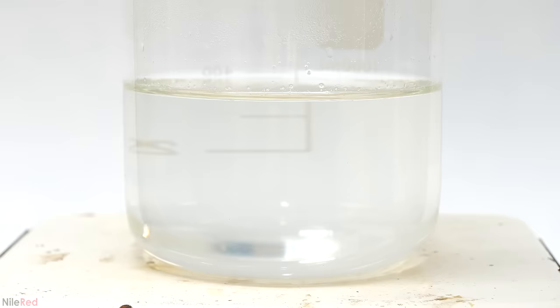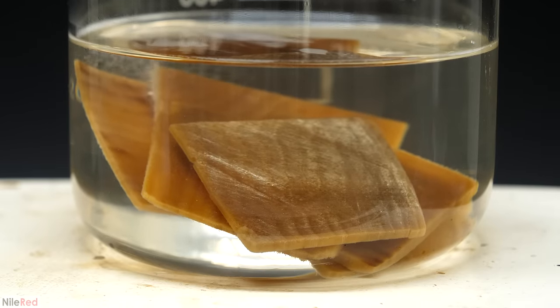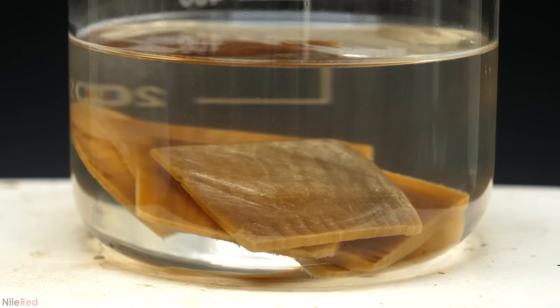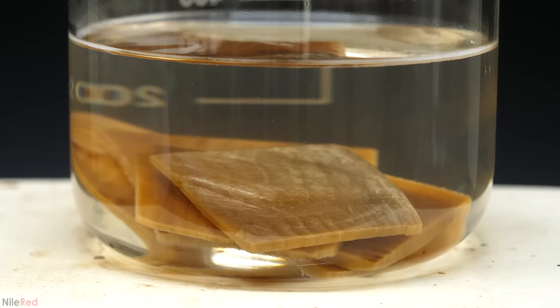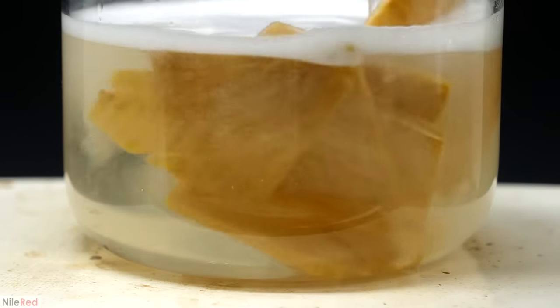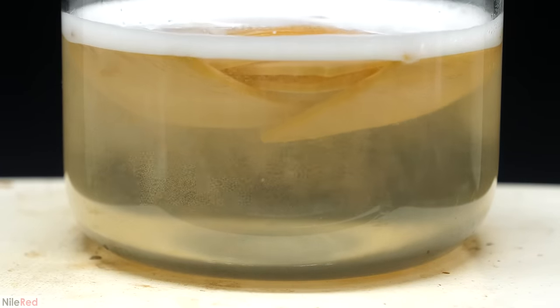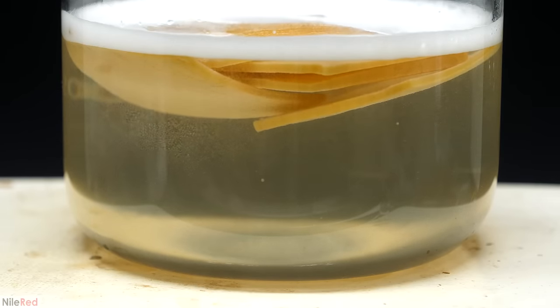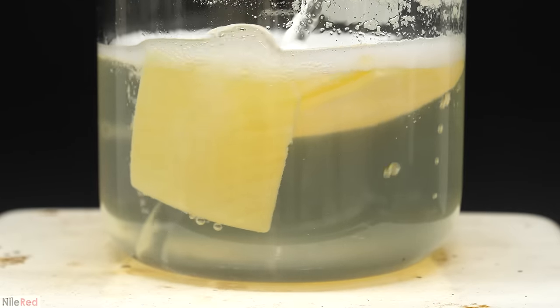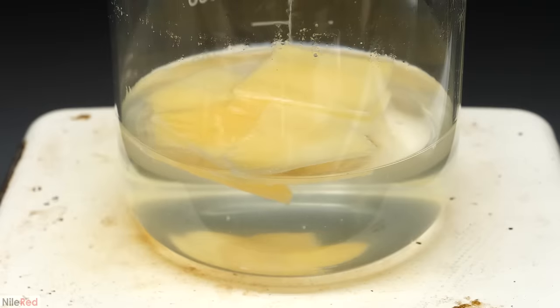They were then treated just like last time - first step was to remove most of the lignin. Then I treated with peroxide, but this time I added the peroxide slowly and started with a cold solution, slowly bringing it to a boil, and it never ended up bubbling out of control. However, even after boiling it for almost the same amount of time, it never fully whitened. Now I'm thinking it was because the thinner pieces were way easier to wash, so all the sodium hydroxide was removed - and because of this, there was little to none left over to catalyze the breakdown of the peroxide, which was important for generating oxygen gas in the wood and destroying the rest of the lignin.